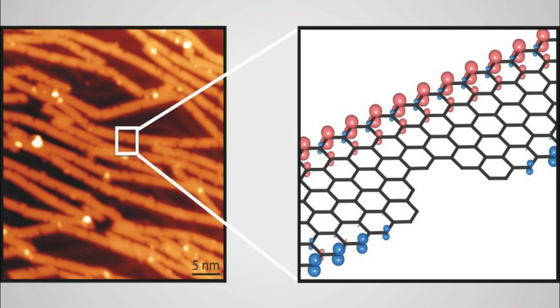And it has been shown that electronic and magnetic structures can be modulated to a large extent by, for example, charge doping, electric fields, lattice deformations, or defect engineering. The combination of tunable magnetic correlations, sizable bandgap width, and weak spin-orbit interactions has made these ZGNRs promising candidates for spin logic operations. The study specifically looks at 6 carbon zigzag lines wide graphene nanoribbons, 6ZGNRs, the only width of ZGNRs that has been achieved with a bottom-up approach so far.